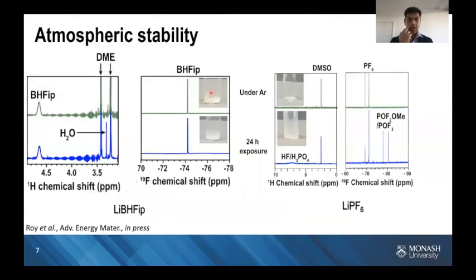So in the next phase, what I have been interested in doing is exploring its atmospheric stability. The instability of hexafluorophosphate is quite well known, and I have exposed a certain amount of PF6 salt under atmospheric conditions on a benchtop for 24 hours. And as expected, we can see quite prominent formations of HF or phosphoric acid, which probably would have resulted from the hydrolysis of PF6 salt. And then there is evidence of decomposition products forming in the fluorine NMR spectra as well.